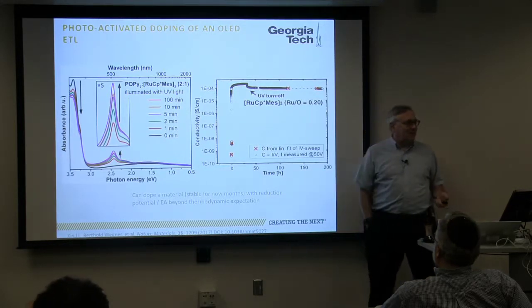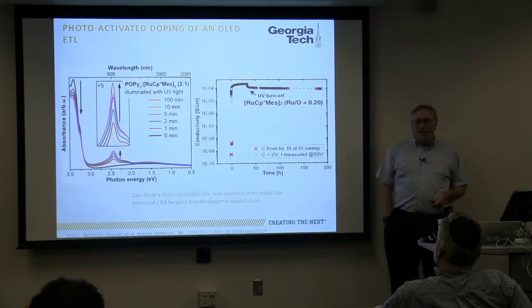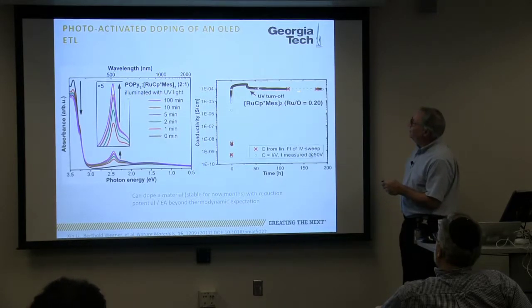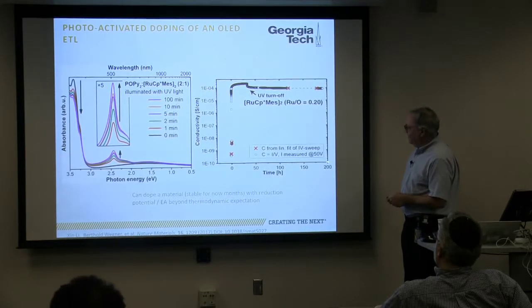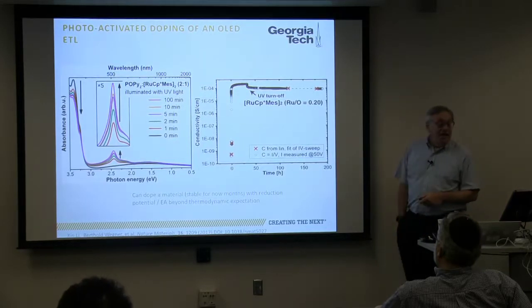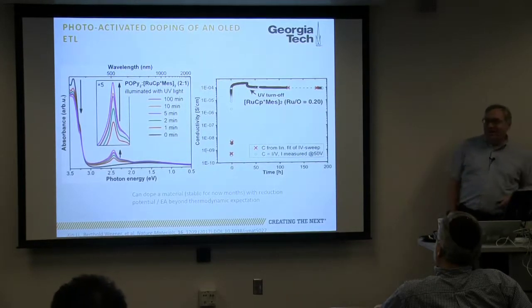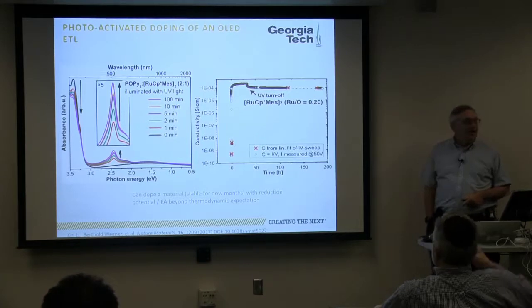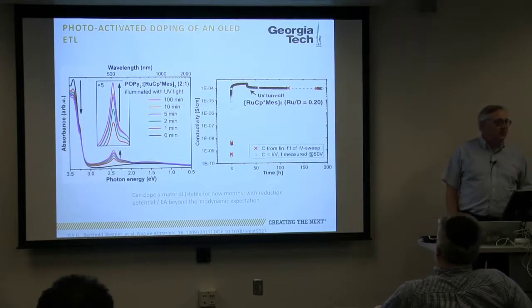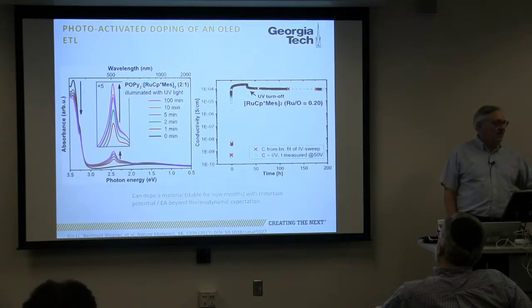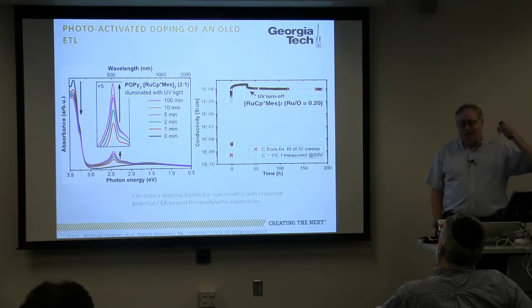That's not that surprising with the light on. What was surprising is that when we turn the light off, it stays for 100 hours. And in fact, we've now looked at this over 9,600 hours, and we only lose about 2 orders of magnitude of the 5 or 6 in conductivity after a year.